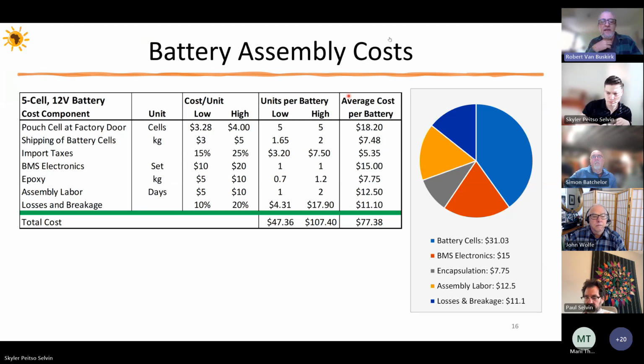The shipping of the battery cells is another $7.50 more or less. There's import taxes when you ship anything. The BMS electronics winds up being about $15. The epoxy is about $7.75. The assembly labor is about $12.50. And if you account for losses and breakage, that's valued at about $11.10.